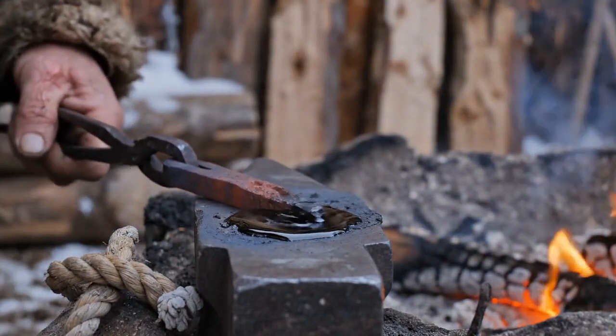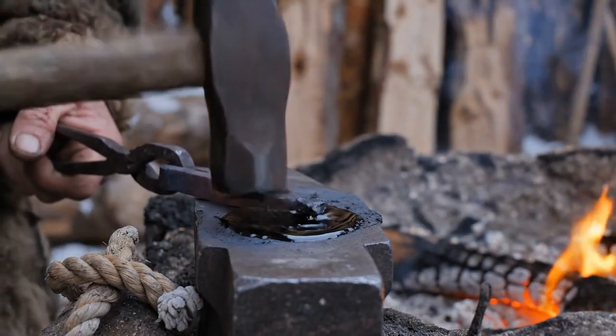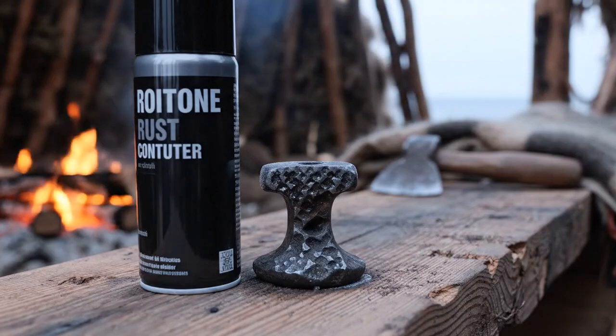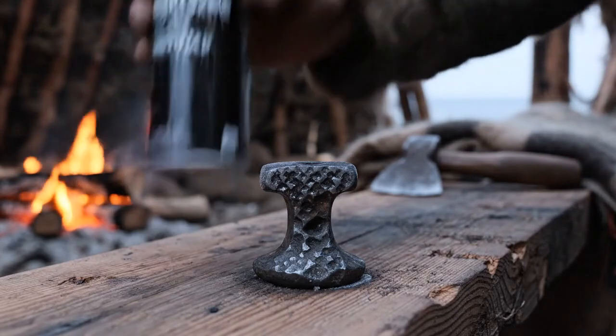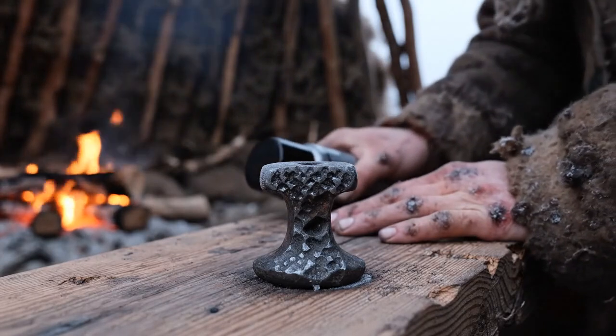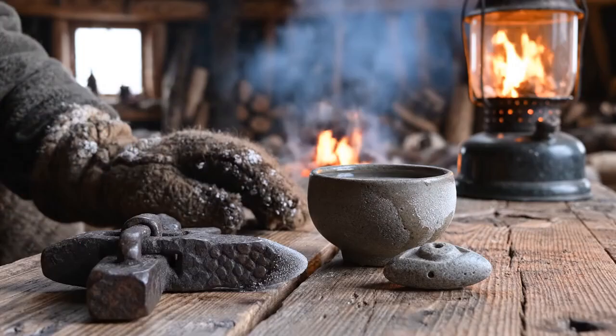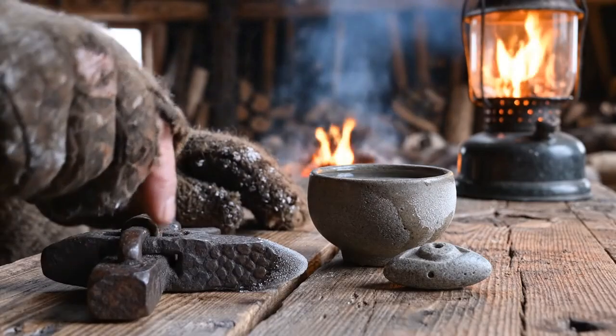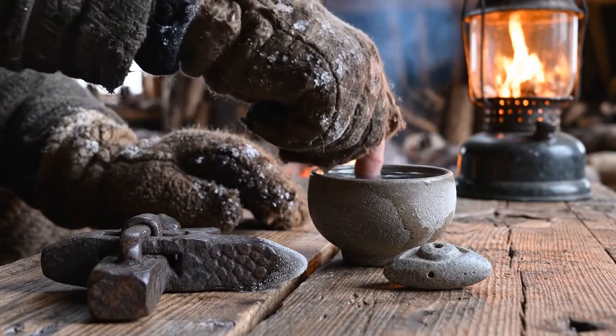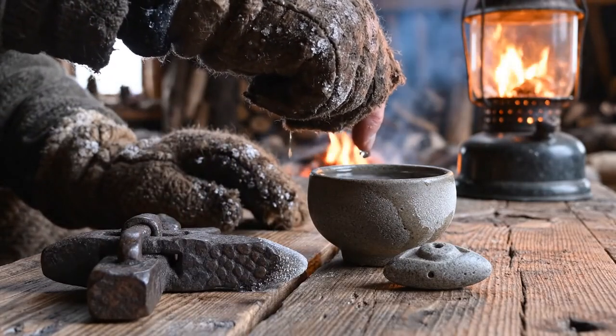The iron rivets from the Gokstad ship are still in Oslo. They are still intact. The black surface treatment Nicolai Nicolaisen found bonded to them in 1882 is still there today, not because of preservation efforts, not because of controlled storage conditions, because the chemistry was correct the first time and has required no correction since.